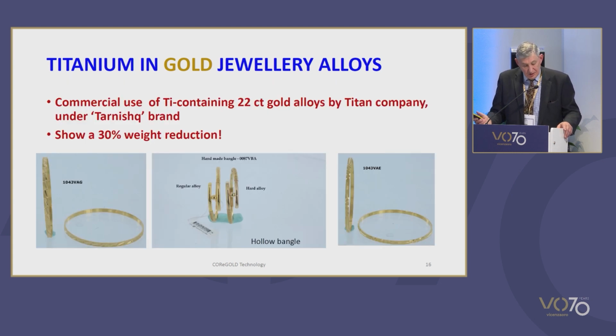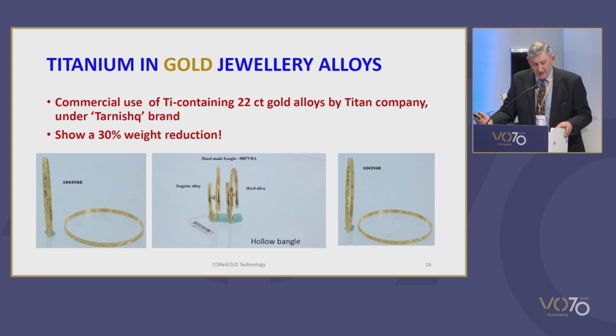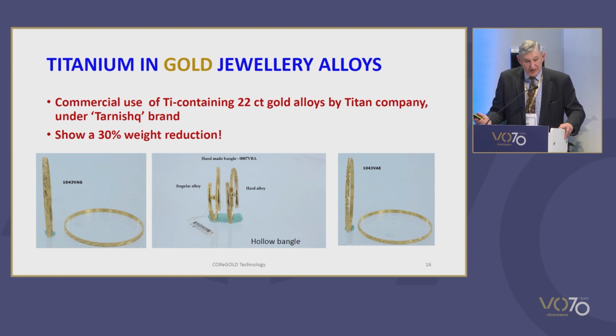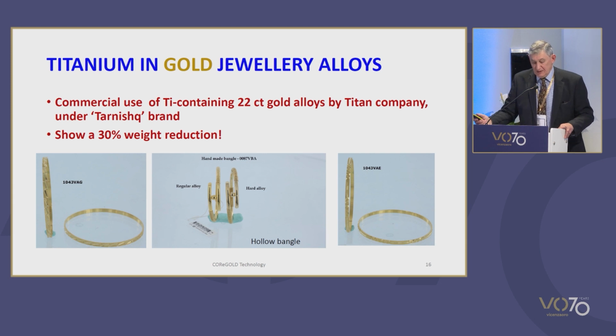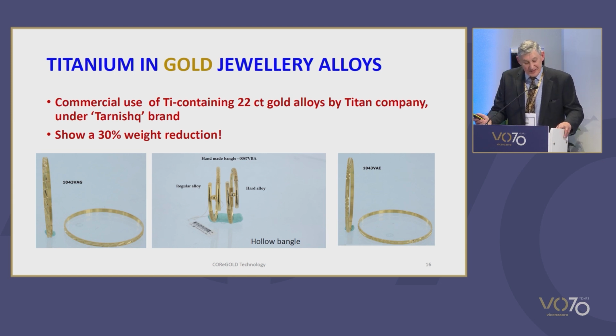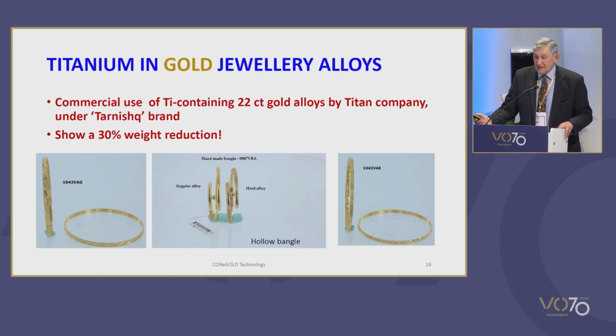The commercial use of a 22 carat gold alloy strengthened by titanium based on this work by the Titan company in India under their Tanishq brand has allowed jewellery products to be marketed that show a 30% weight reduction compared to conventional 22 carat gold alloy, as we can see in the figure. The centre picture shows a hollow bangle in their new alloy compared to a conventional 22 carat gold alloy bangle. And this is an example of where there's considerable weight saving.